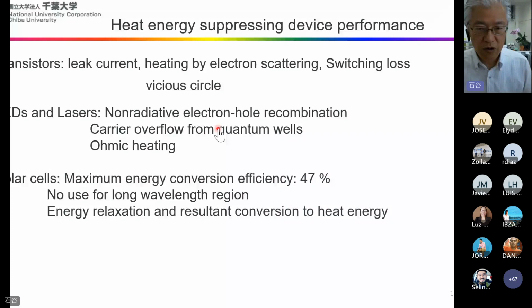And for solar cells, the maximum energy conversion efficiency is 47%, but this is at the research stage, not in practical use. In this case, there is no use of the long wavelength region. And for the short wavelength region, because of the energy relaxation of electrons from the excited level to the band bottom, heating energy takes place, and this heat energy is wasted. This is the main loss, and because of this, the top value is less than 50%. So if we can utilize the heat energy in solar cells, the energy conversion efficiency will be improved much more.